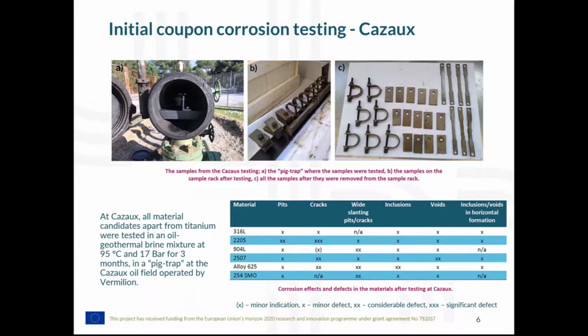And then we continue to Cazaux, in southwestern France, which is an oil field operated by Vermilion, so Eric, and there we tested all material candidates apart from titanium in an oil and geothermal brine mixture at 95 degrees and 17 bar pressure for 3 months